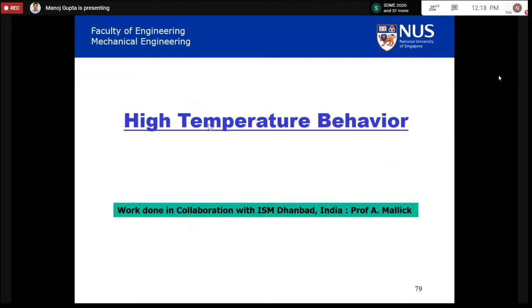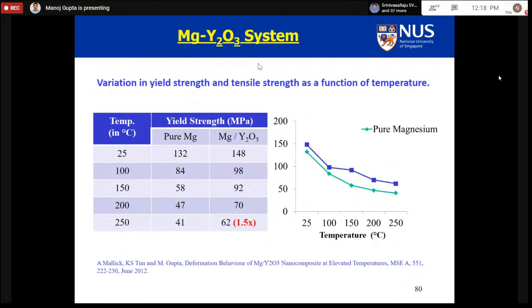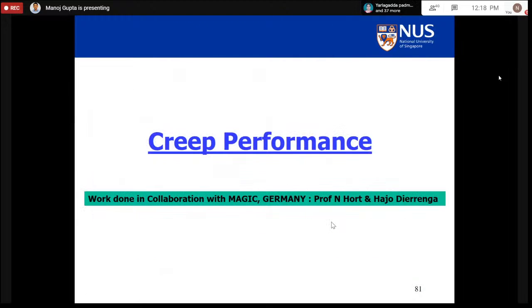Sometimes you want to use your material at elevated temperature, and this is where we did some work with ISM Dhanbad with Professor Malik there, and we worked on magnesium yttria system, and we found that up to about 250 degrees centigrade, the strength of your nanocomposite remains 1.5 times higher than that of the monolithic material, and the graph shows this relation of the temperature and the strength, where the composite is always superior to that of